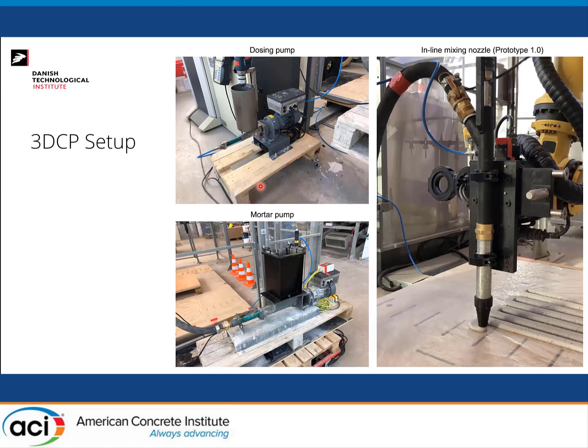And how do these two pumps come together? They come together at a nozzle. So I have a mixing shaft that is about 25 centimeters long, which means for the normal pumping rates, the mixing time within this chamber, from the injection point that's here up to the extrusion point all the way down, is about 15 seconds. Of course, it would depend on the flow rates you're operating with, but for the numbers we work with, it's about 15 seconds.